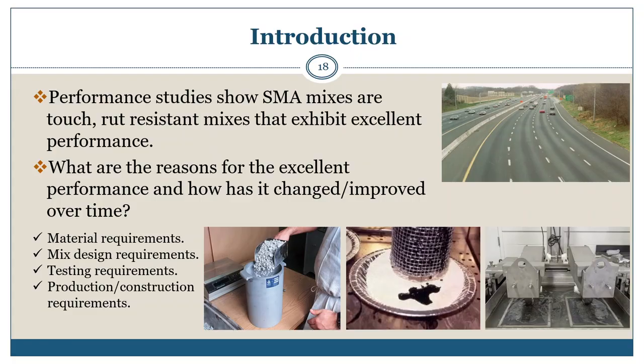In the presenter's opinion and observations from other performance studies, SMA mixtures consistently exhibit lower rut depths, less cracking, which includes predominantly top-down fatigue cracking and transverse cracks, and much less crack deterioration along the edges of the crack when they do occur. In fact, that is a very significant benefit of SMA mixtures for reducing crack deterioration as compared to conventional dense graded mixtures.